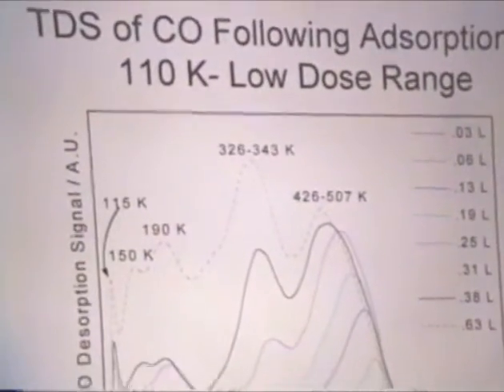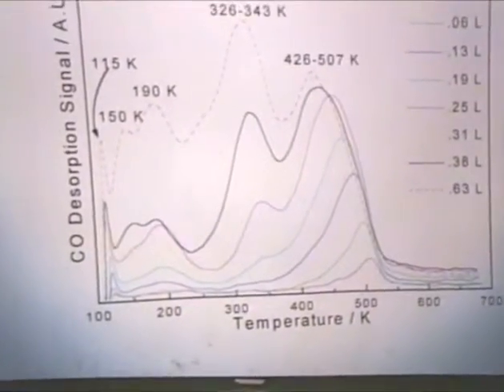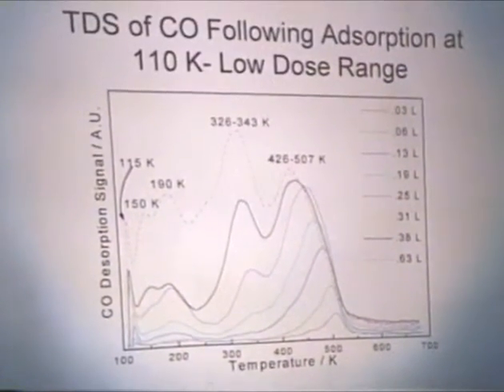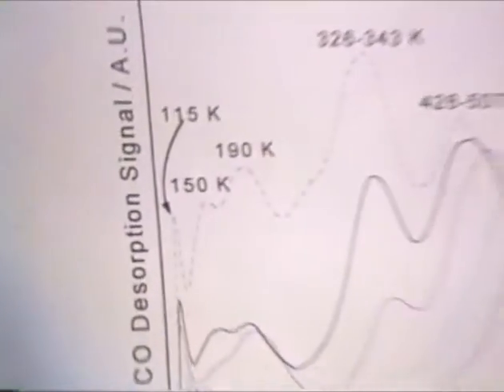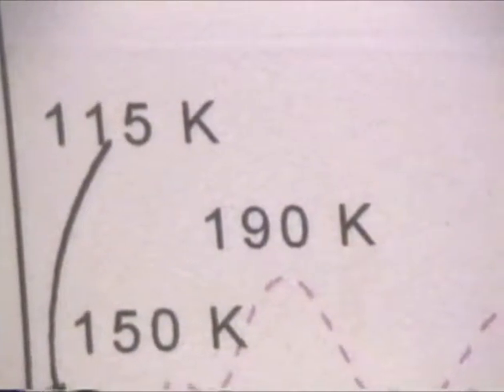So for our thermal desorption studies, obviously one thing we were looking for was to see if we saw any molecular versus dissociated CO. And this is the thermodesorption results following adsorption at 110 Kelvin across a low dose range. For all of our thermodesorption experiments, the background pressure before dosing was less than 1 times 10 to the minus 10 millibar. We were cooling the chambers cryogenically. And a heating rate of 2 Kelvin per second was used for all experiments.